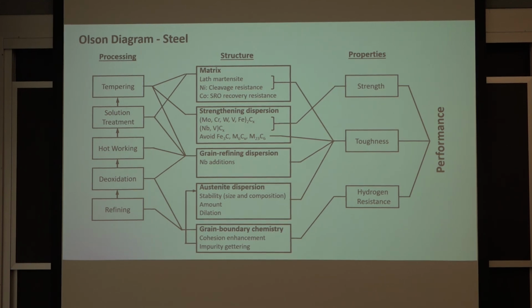In the case of steel, you would heat that up to a temperature again where you would transform all the ferrite and pearlite into austenite, and then you would quench that. During the quenching process, there's not enough time for that material to turn back into ferrite again, so it turns into what's called martensite.